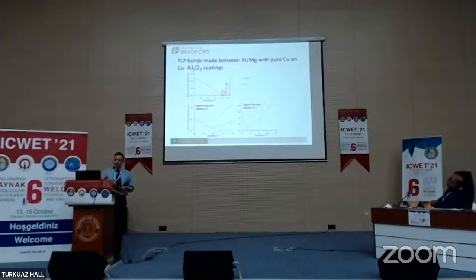So this shift in our eutectic temperature means that the solidification process starts much faster. And this is why we think that we get a change in our eutectic width and a change in the strength.